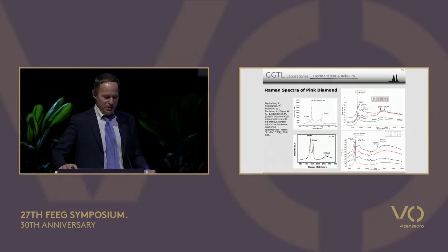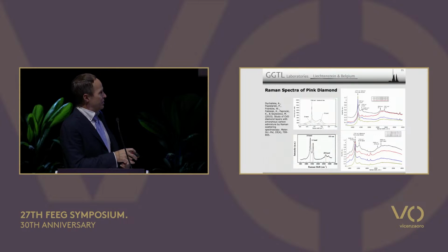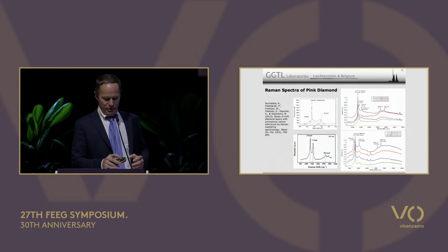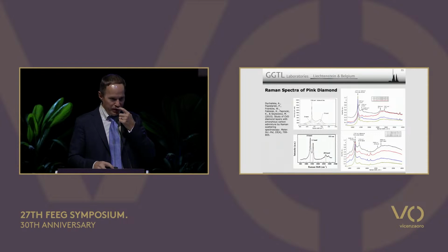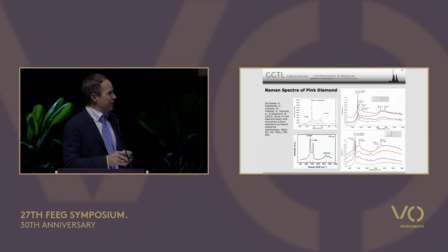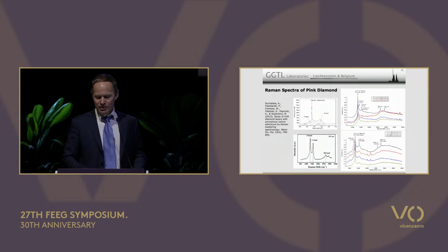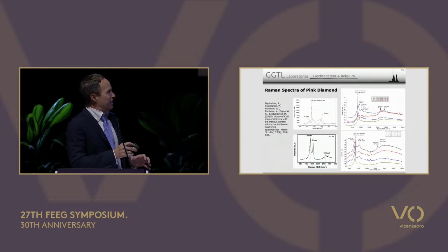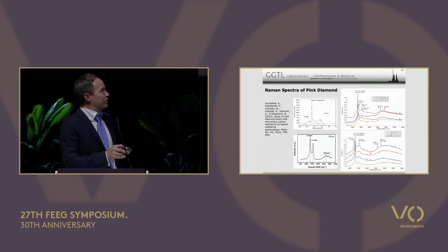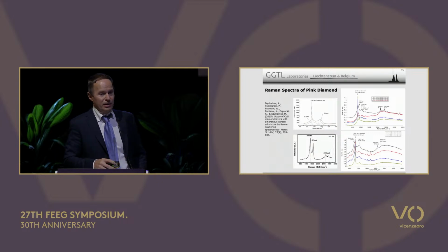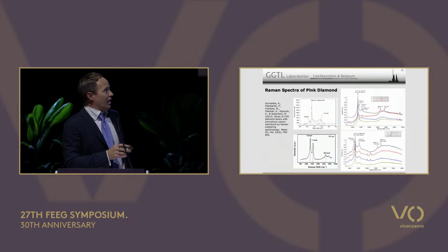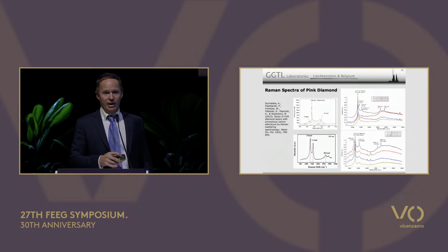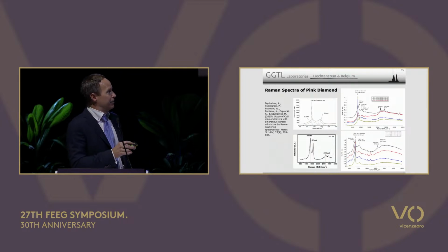Now, this is a short intermezzo to show you something that just got cleared up during this study: pink diamonds have a very strange photoluminescence spectrum. This is a 532 nanometer spectrum. This is a 635 nanometer spectrum. These spectra are almost the same at room temperature as they are at low temperature. And I always wondered why this was. Why do we have these strange bands?